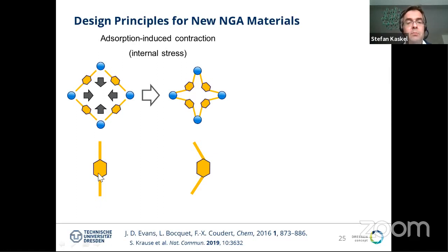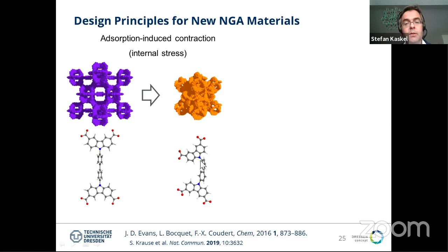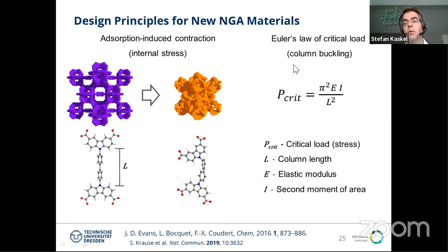And here we have basically this buckling behavior, which in the linker looks like this. So we go from a straight form to a buckled form, quite twisted form. And Jack Evans basically developed a model here, which relates to the Euler's law of the critical load. It's basically in buildings when you have two stories and you have a column in between, it gives you the estimation of a critical pressure that is needed to buckle the column. And this buckling behavior of the column depends on the various constants here, elastic modulus and so on. But it also, and I would only like to point out today, it also depends on the column length. And this is a critical aspect here.